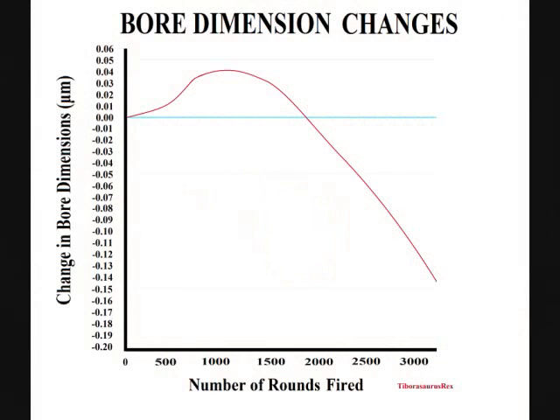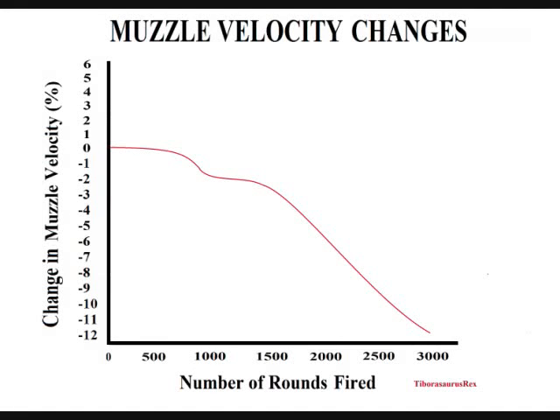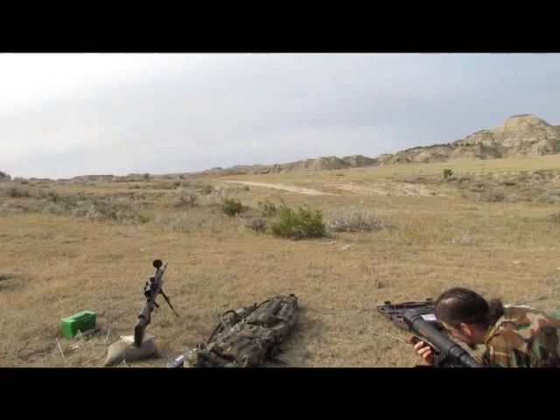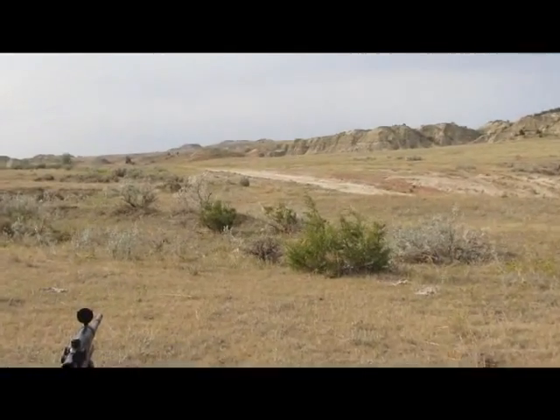And this can accelerate erosion, particularly towards the end of a barrel's life, more than at the beginning of a barrel's life. That's really what starts to render a barrel useless after a while, once you start having significant gas leak around the projectile as it's moving down the bore. You have jetting, and you're not only going to have a loss of gas pressure and a loss of muzzle velocity due to that jetting, you're going to have less of that gas being used to push the bullet forward. It's just burning a hole around the side of the bullet, and that's going to make a mess out of your bore. So that's kind of when you know your bore is done, when you have a lot of jetting action going on, and that'll be marked usually by a wild inaccuracy or by a significant drop in muzzle velocity towards the end of a barrel's life.